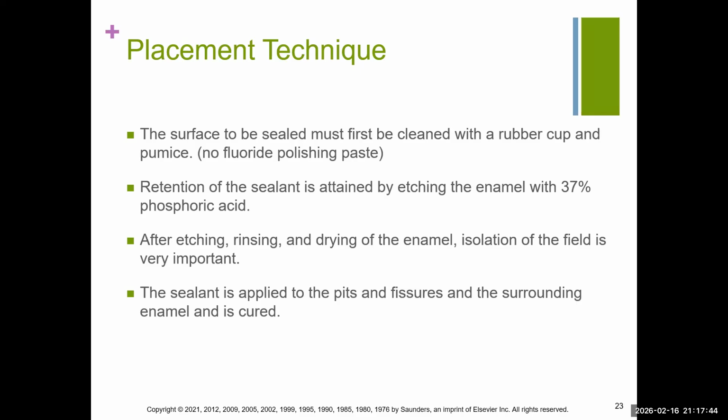The surface to be sealed must first be cleaned with a rubber cup and pumice. No, fluoride is not preferred, okay? Retention of the sealant is then attained when you etch it with 37% phosphoric acid. Then after the etch, you want to rinse, dry, and isolate the field.